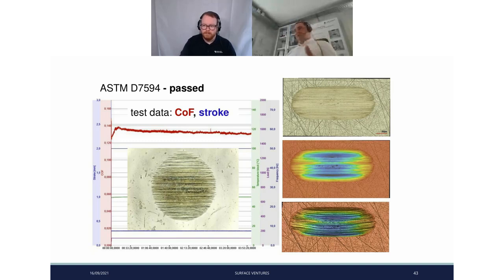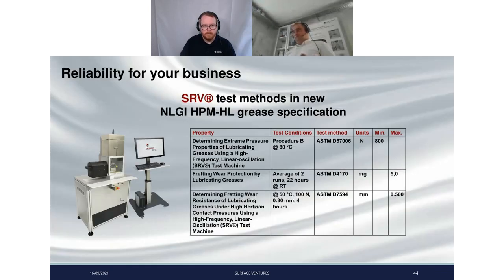On the one hand side, we have the coefficient of friction at the test end, represented in red. Then we have the wear scar diameter and the wear volume on the disc. So three very simple values which describe the system. And as I mentioned already, with the industry standard of the SRV, we are set in many specifications. The newest one was now the HPM specification for high performance multi-purpose greases at the NLGI, and so we are also settled in many other specifications.